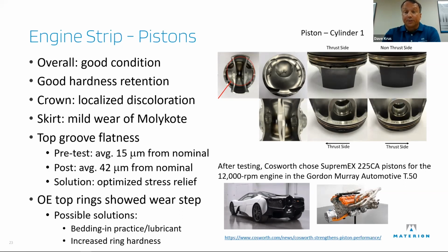But the only thing we noticed was that the top groove went out of flatness a little bit. And working with Cosworth and our brilliant engineers over in the UK where this Supremex is made, we figured that there just needs to be an intermediate heat treatment. You rough it first, do a heat treatment, and then finish machine it. And that actually led them to being able to put this material into the T50, the Gordon Murray T50, which is a 12,000 RPM, 600 and some horsepower, naturally aspirated engine.